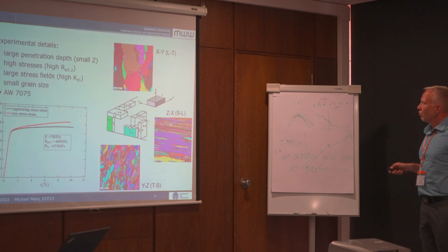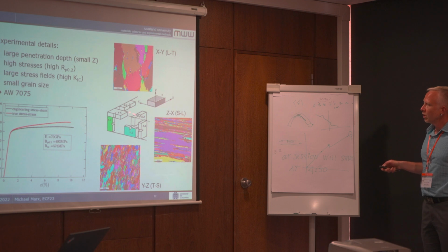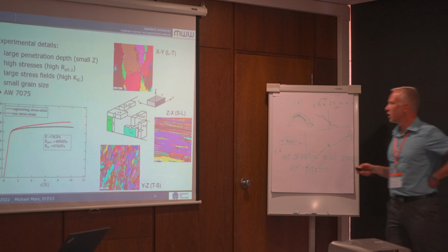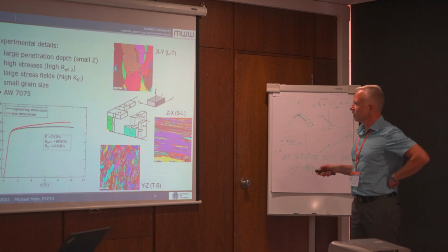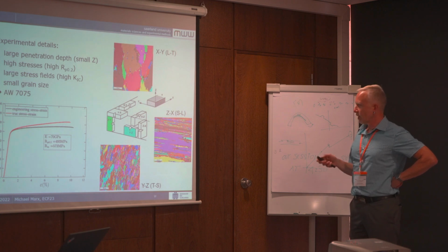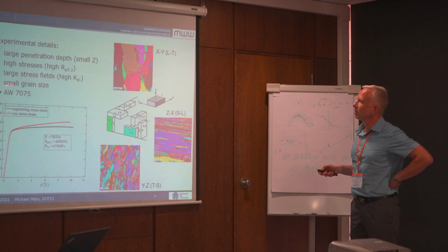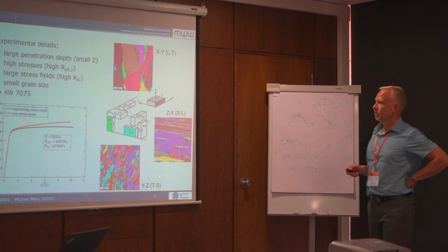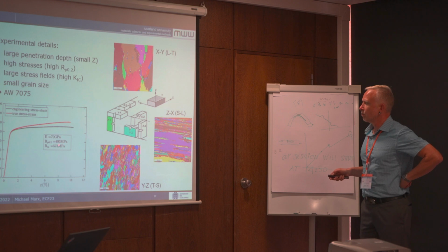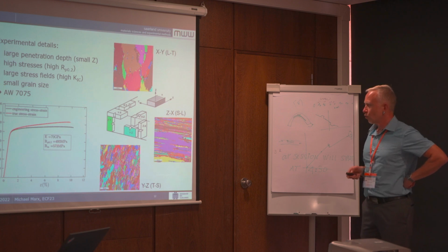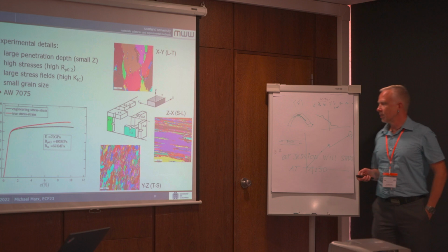In the ZX direction, we have in this direction small grains, but larger grains in this direction. And if we have a look here on this plane, we have a grain size which seems to be okay. So we can cut our specimen in this and in this direction. And here you see the stress strain curves of our material. It was an aluminum alloy 7075 with a yield strength of nearly 500 megapascals and a tensile strength of about 570 megapascals.